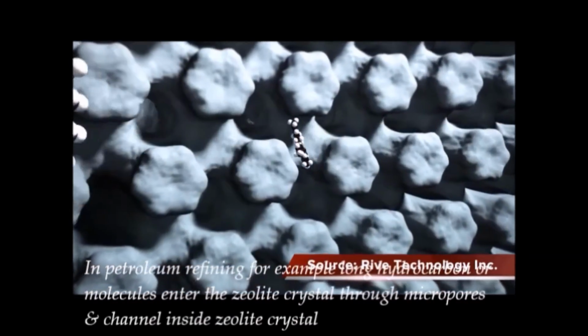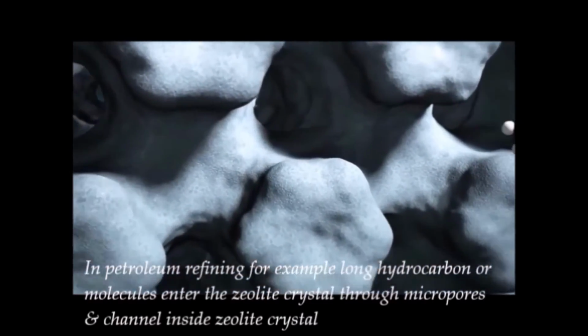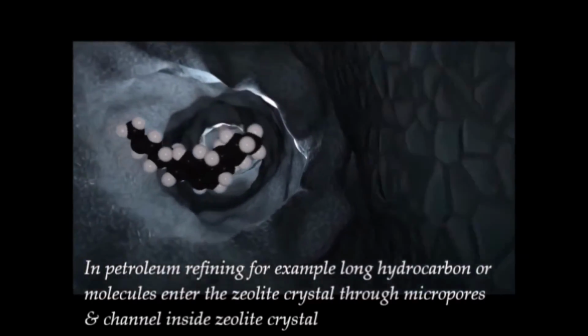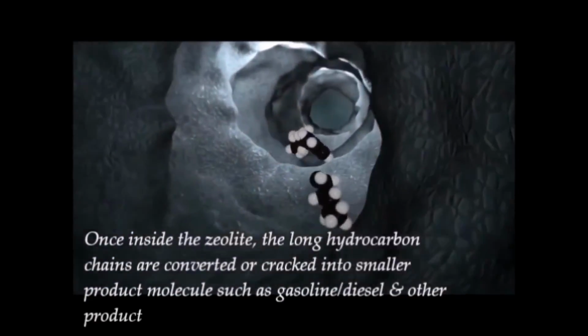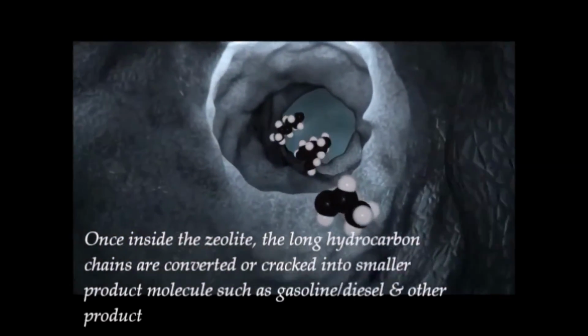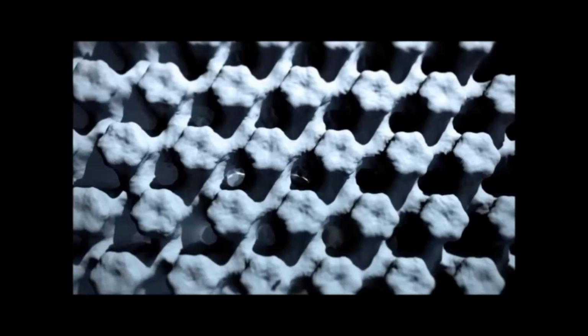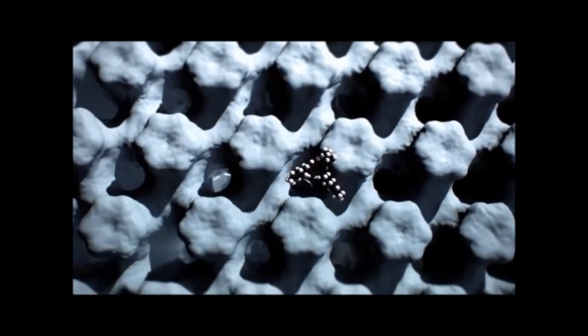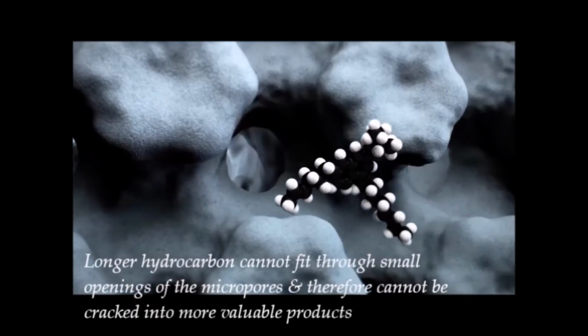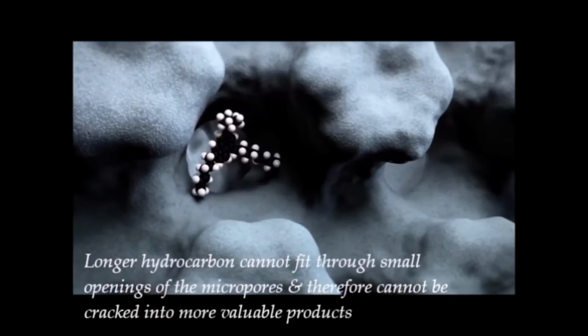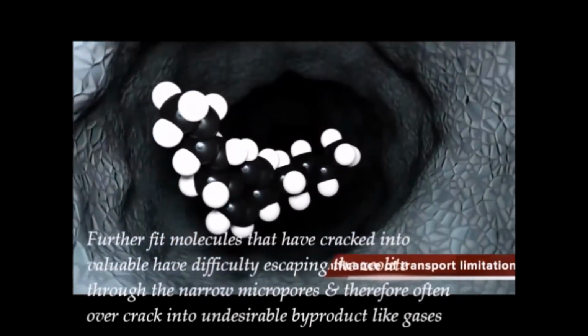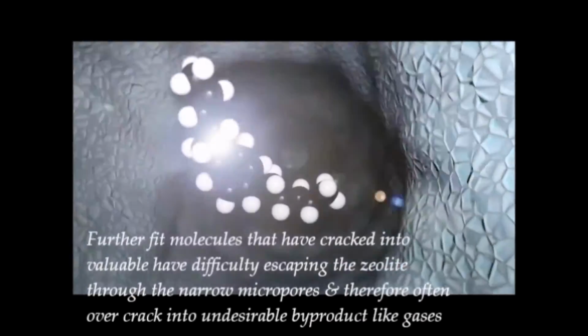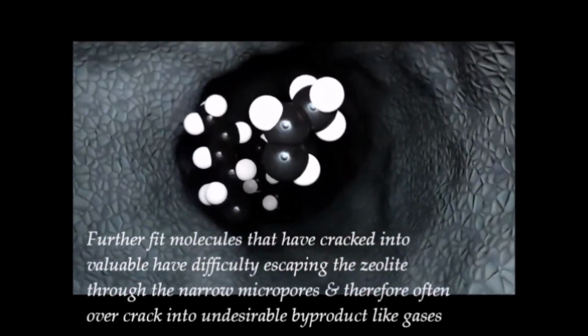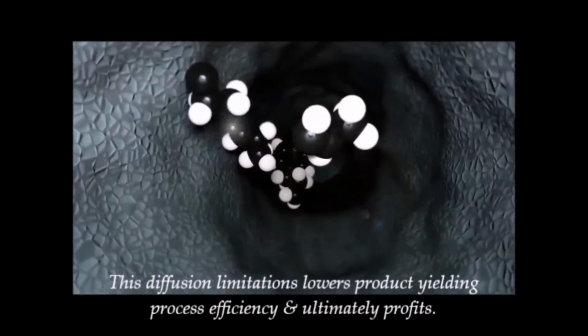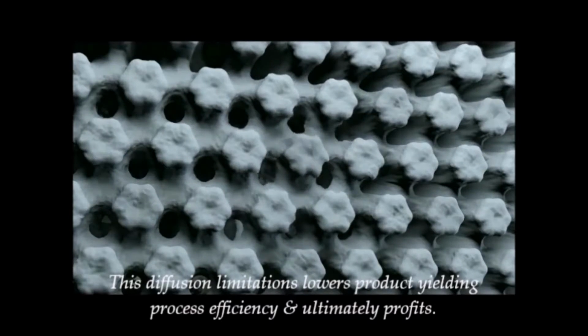In petroleum refining, for example, long hydrocarbon chains or feed molecules enter the zeolite crystal through the micropores and channels to the sites inside the zeolite crystal. Once inside the zeolite, the long hydrocarbon chains are converted or cracked into smaller product molecules such as gasoline and diesel and other products. But today, zeolites suffer from a fundamental performance limitation due to the size of their micropores. Longer hydrocarbons cannot fit through the small openings of the micropores and therefore cannot be cracked into more valuable products. Further, feed molecules that have cracked into valuable products have difficulty escaping the zeolite through the narrow micropores and therefore often overcrack into undesirable byproducts like gases. These diffusion limitations lower product yield, process efficiency and ultimately profits.